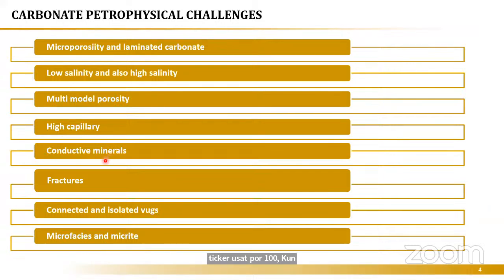Conductive minerals. One of the most famous conductive minerals are pyrite and siderite. Pyrite is iron sulfide and siderite is FeCO3, an iron carbonate mineral. Both of them are present in some carbonates. You need to take care of that. A spectroscopy tool will tell you if you have pyrite and siderite. From the volumes obtained from the spectroscopy, you will apply a correction equation to correct your resistivity, not your saturation. And I use this equation a lot by integrating the spectroscopy with my triple combo.